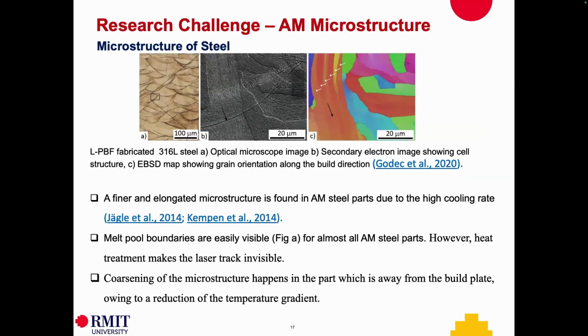Then, if we look at the steel, which is a key focus for AM for different applications, normally we find finer and elongated microstructures. Melt pool boundaries can be easily found and are easily distinguishable. But if we use suitable heat treatment, we can make the laser tracks disappear. So coarsening of microstructure happens farther from the build plate. So what we get here for steel in the literature is a gradient microstructure, a fine scale microstructure close to the build plate, and it becomes coarse as we move far away from it.